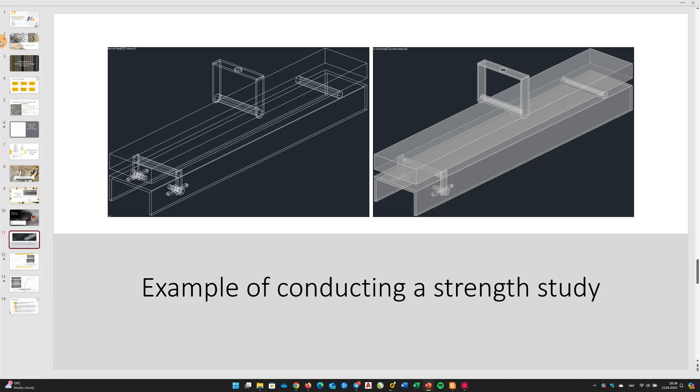The determination of the force parameters of reinforced specimens was carried out according to the recommendations of the National Standard of Ukraine: Determination of the strength limit under bending with concentrated load. The specimens were placed in the center on support rollers as shown in figure. The roller load was applied in the middle of the specimen. The load applied to the blank was increased uniformly at a rate of 0.5 MPa until the moment of sample failure.